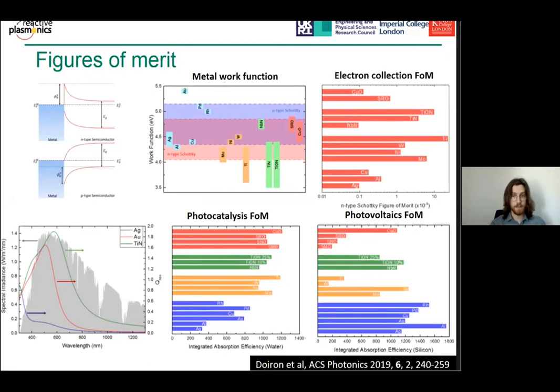We can also consider solar energy harvesting. So we can see that different materials absorb at different wavelengths of the solar spectrum. So we're comparing here silver, gold, and titanium nitride. And these are nanoparticles that are 80 nanometers in diameter. And again, we can consider their absorption cross-sections in order to identify which material would be most suitable for photocatalytic applications or photovoltaics.